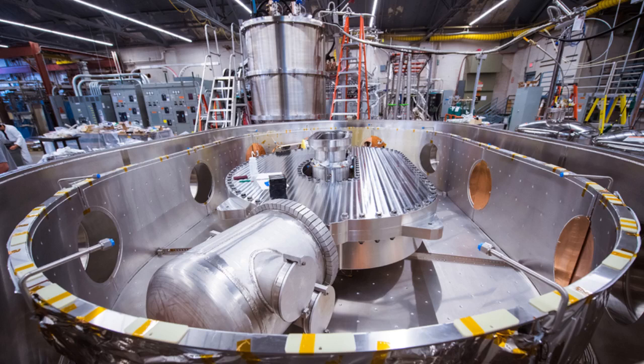The new papers in Transactions on Applied Superconductivity describe the details of that redesign process. One of the dramatic innovations — which had many others in the field skeptical of its chances of success — was the elimination of insulation around the thin, flat ribbons of superconducting tape that formed the magnet. Like virtually all electrical wires, conventional superconducting magnets are fully protected by insulating material to prevent short circuits between the wires. But in the new magnet, the tape was left completely bare, and the engineers relied on REBCO's much greater conductivity to keep the current flowing through the material.